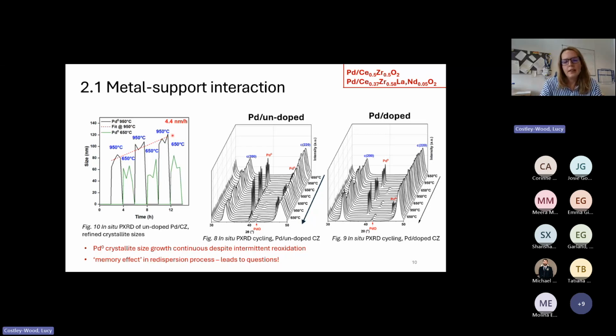One question that this led to is: is all of our palladium metal really oxidizing, particularly on the rare earth doped material here, where we have no palladium metal reflections at the lower temperature? Does that mean that we've oxidized all our palladium, or is the palladium metal which is left too dispersed or insufficiently crystalline to be visible by powder diffraction? So we repeated one temperature cycle.